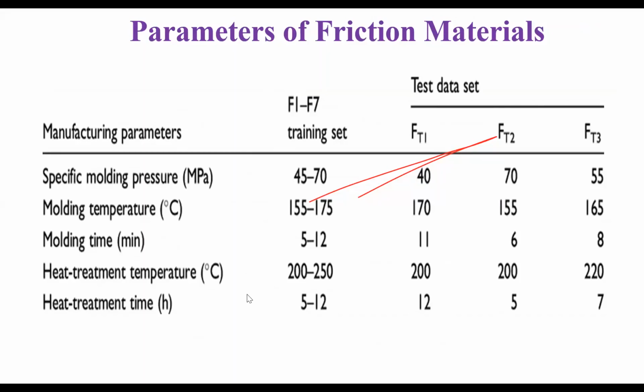So we have different parameters of the friction material, based on the manufacturing process. This is some set of readings taken for 7 trials, 1 to 7 trials, and these are the average values with respect to the specific molding pressure in terms of MPa, molding temperature in degrees Celsius, molding time in minutes, heat treatment temperature, and also heat treatment time in hours. These are some of the readings taken only for the first three, and FT4, FT5 are not shown here. And this is the average value.